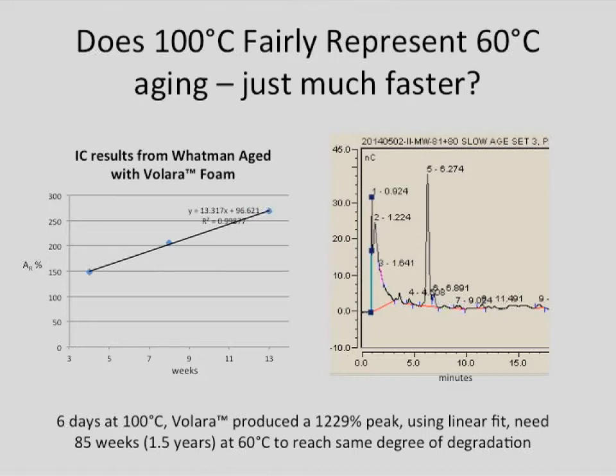So what we did to check was we took one of the foams that we had tested at 100 degrees and put it into an oven at 60, taking a sample out of a new jar every few weeks, for about 13 weeks.